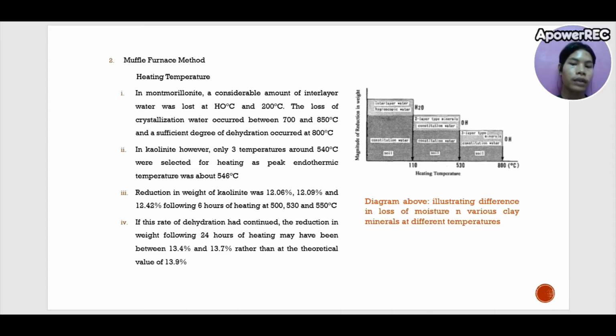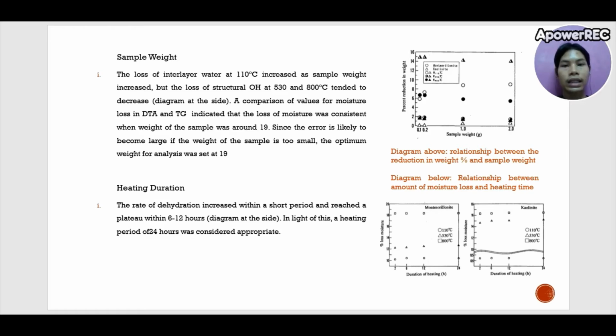If this rate of dehydration had continued, the reduction in weight following 24 hours of heating may have been between 13.4 and 13.7 percent, rather than a theoretical value of 13.9%. Okay, so second is the sample weight.